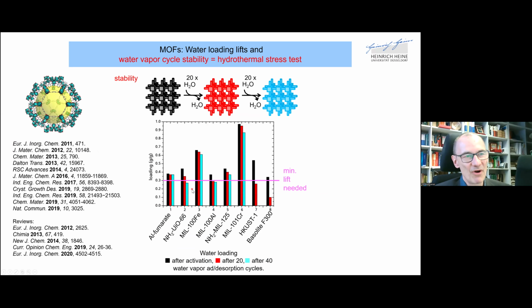So in our work, once we had got started, we looked at prototypical MOFs, how they would perform in terms of loading lift, and then the stability, of course, was an important issue. So 3 MOFs stick out here. MIL-101 because of its high uptake, MIL-100 iron because it has also quite a high uptake, and aluminum fumarate, whose uptake is not so high anymore, but it's very stable. So there is no degradation, no loss of uptake capacity over 2 times 20, or overall 40, uptake and desorption cycles, which we measured.